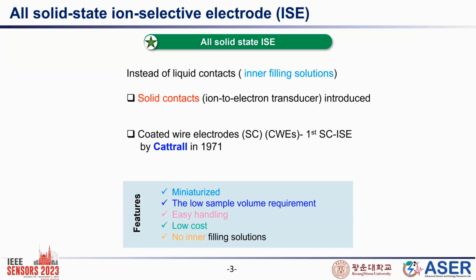But our goal is due to some disadvantages of the first reported sensor, that was the potential dip due to a potential generated between the ion selective membrane and the current collector. So we are trying to minimize the potential dip, and by incorporating some kinds of nanomaterials, we can achieve a very stable output response. The all-solid-state ion selective electrode has some features. It is miniature, as I already said, requires low sample volume, low cost, and one great point is that no inner filling solution is required.